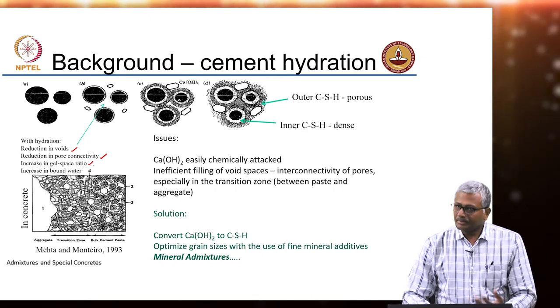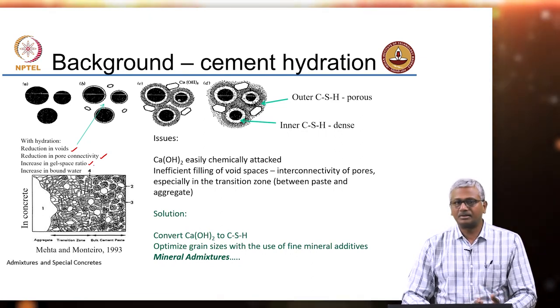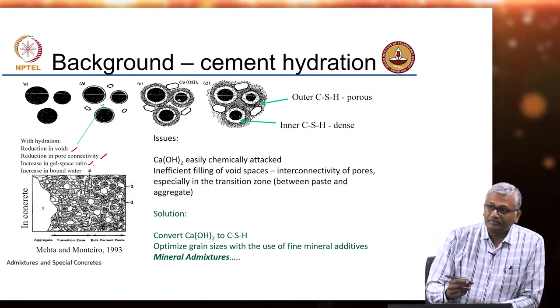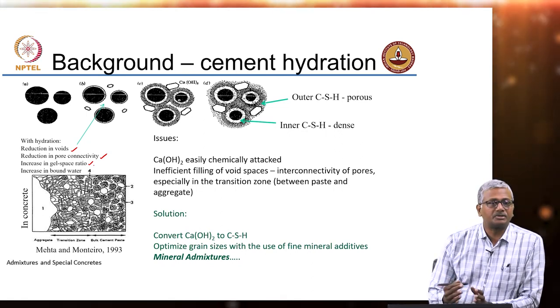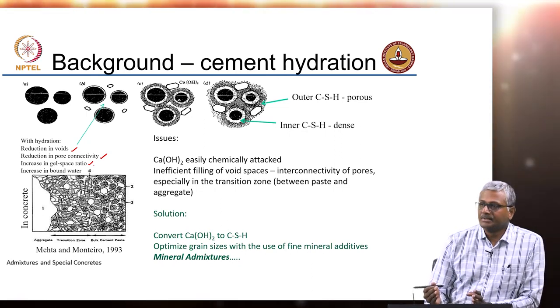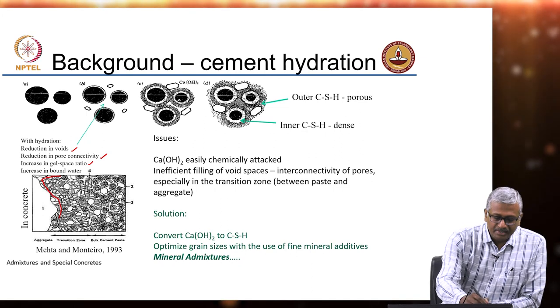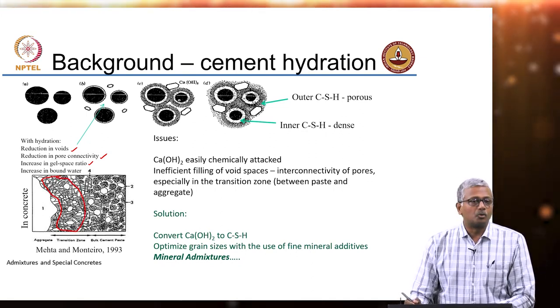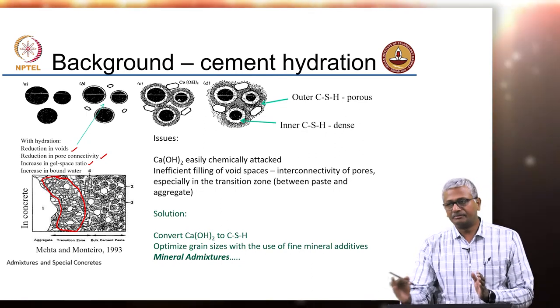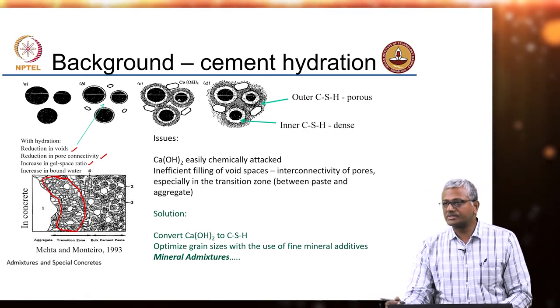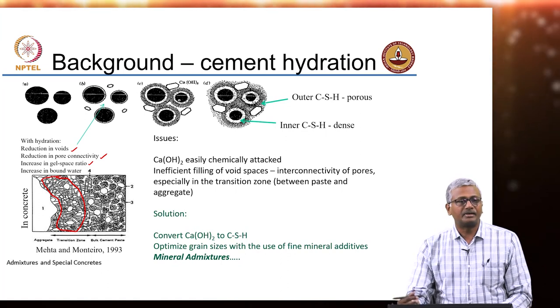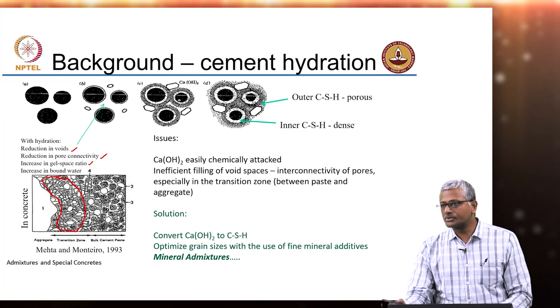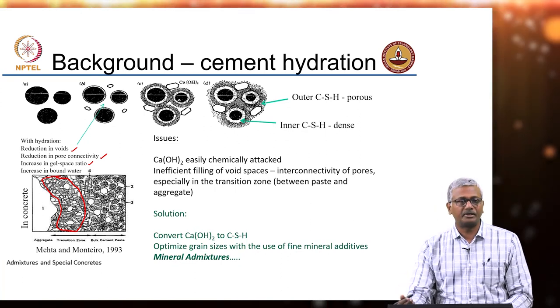In regular concrete, the way we mix paste and aggregate leads to microstructural variations where the zone next to the aggregate is usually much more porous compared to the zone further away from the aggregate. We call this concept the interfacial transition zone, and very often this is a cause for most of the issues related to strength and durability of concrete.